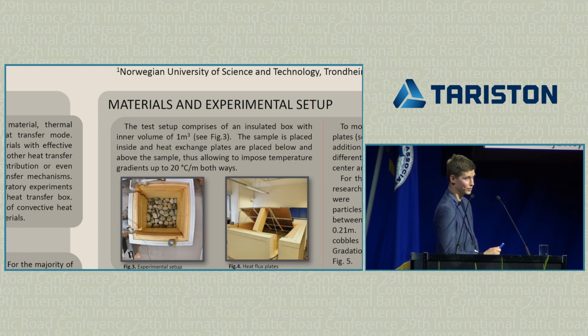This in particular was a kind of trial study. We filled the box with cobbles, which is not a typical road construction material. The purpose of doing that was that we have some other data that we can compare with. So the material is put inside a box. On the right-hand side, you can see those are heat flux devices. So they're measuring the energy which flows through the sample. Different temperatures are applied at the top and the bottom.